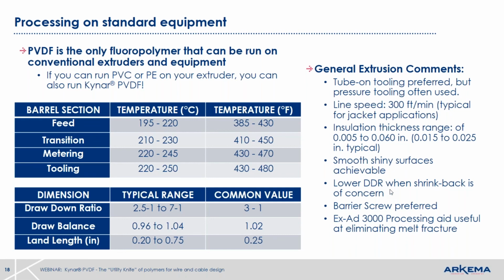We always recommend a lower drawdown ratio. If shrink back is a concern, we always recommend barrier screws rather than metering screws. So this just gives you a thumbnail idea: if you don't have a fluoropolymer machine, you can run PVDF on a machine that is capable of running PVC or polyethylene. If you want more details, just contact me.